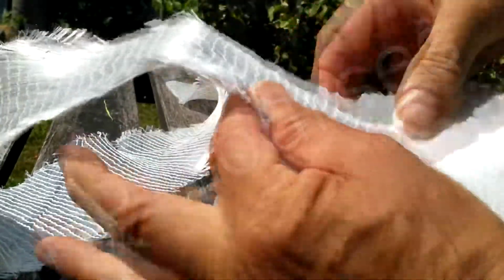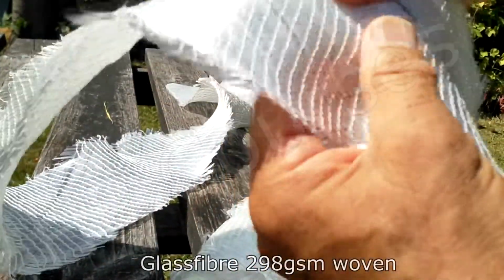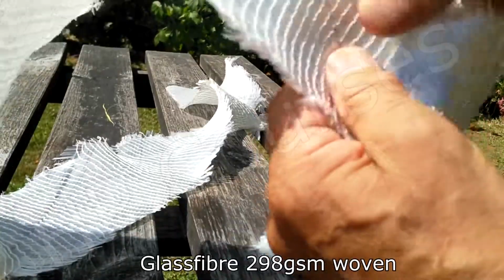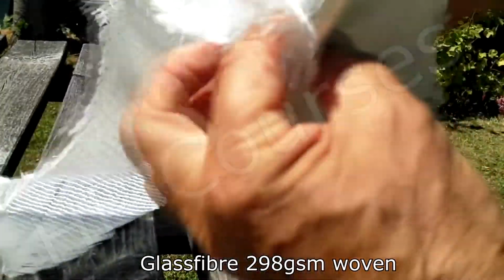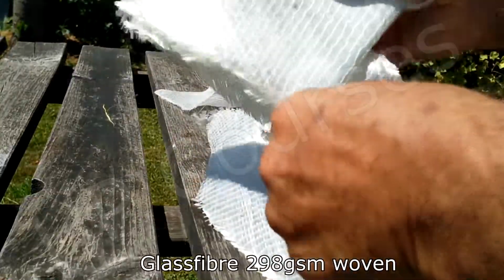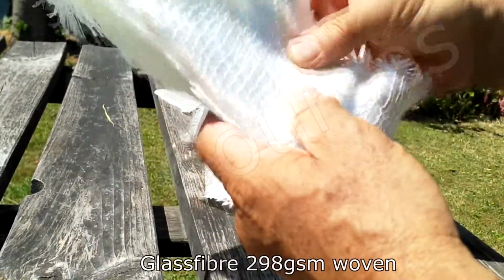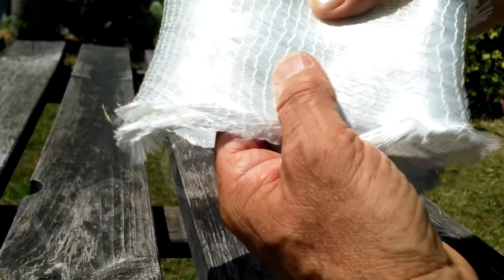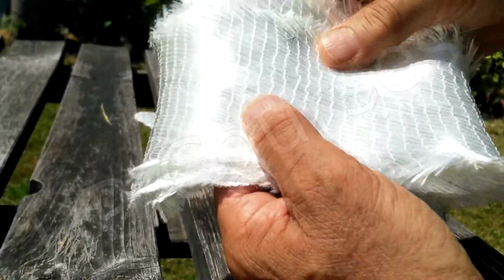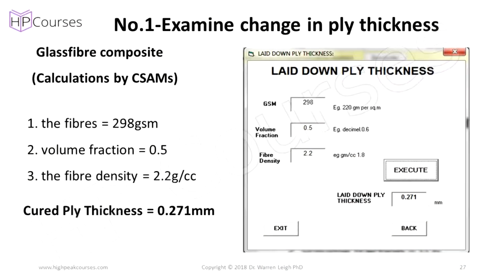First, we will calculate the laid down ply thickness of the glass fibre fabric in a resin matrix. Its areal weight was given at 298 GSM. For the volume fraction of the composite, we initially assume 0.5 for the sake of the calculation. But as previously mentioned, we will check this value by doing a test using the manufacturing process intended for use. Fibre density is given by the fibre manufacturer at 2.2 grams per cc. The calculation using CSAMs shows a laid down ply thickness of 0.271 millimeters.